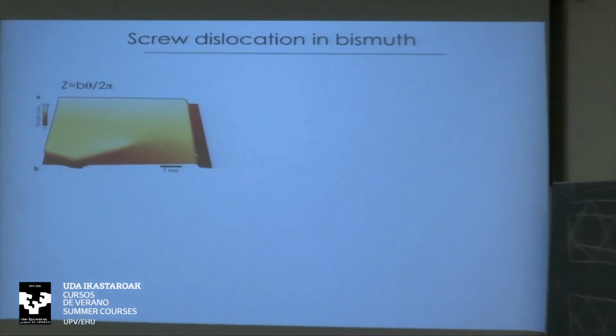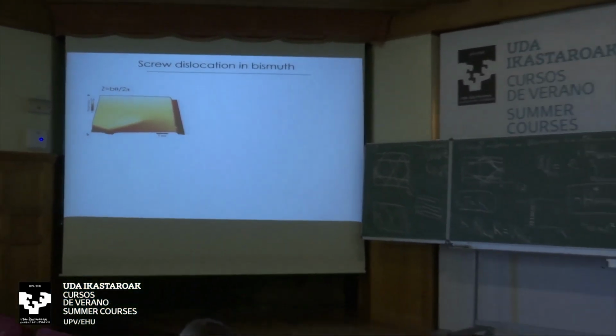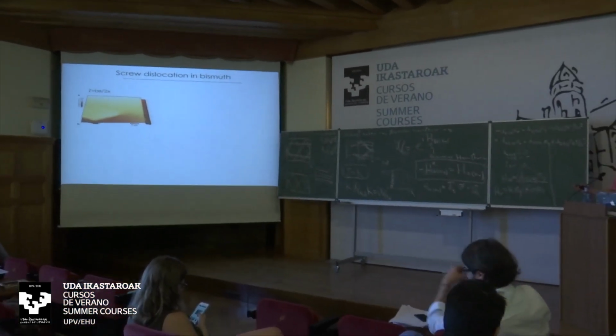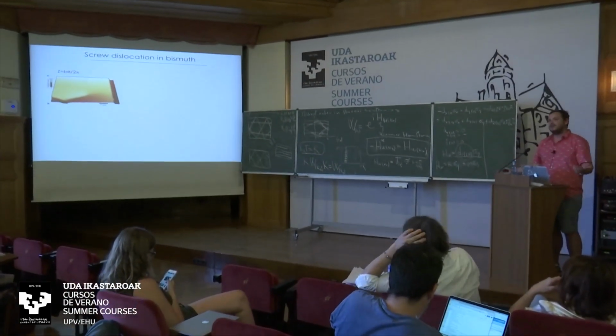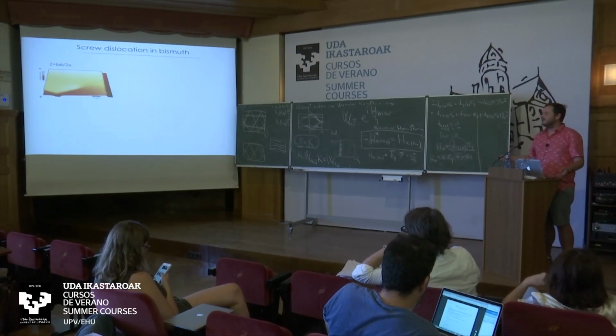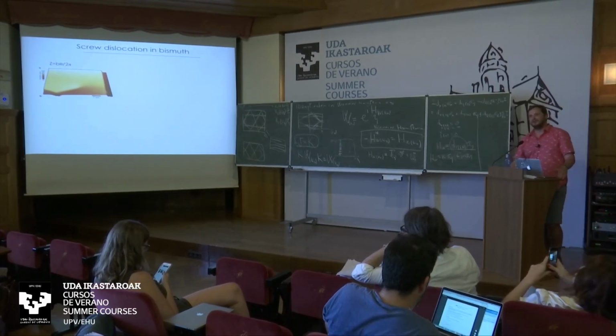So this screw dislocation can be either a very convenient metallic channel, helical, topological, for this edge mode, if the topological phase can support it, or it can be the strongest possible scatterer for this edge mode, if it cannot penetrate into the screw dislocation.